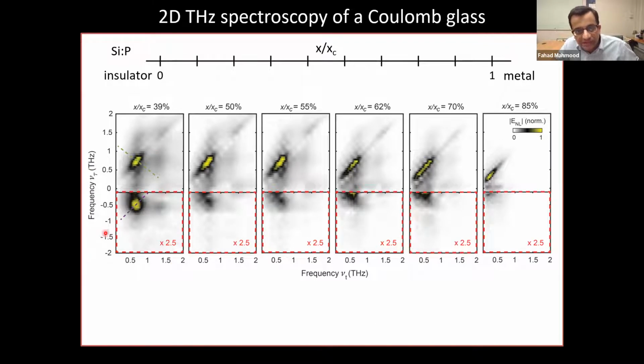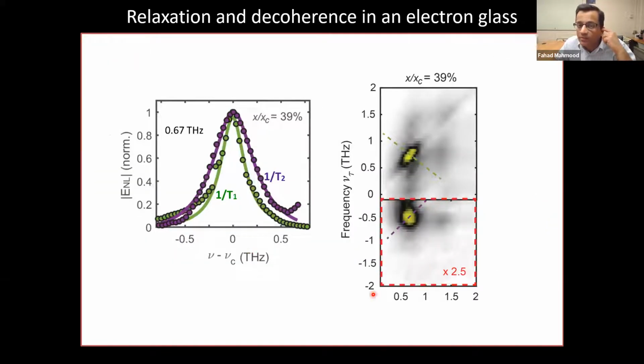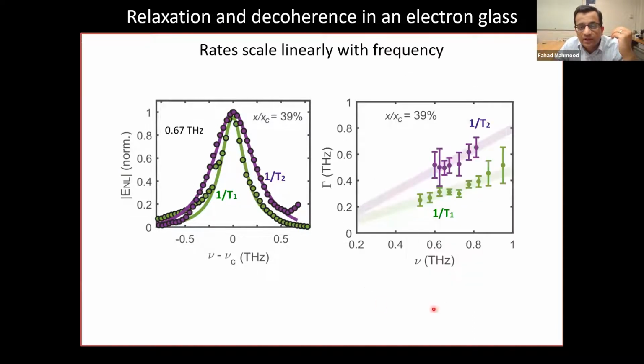We can take these line cuts that I was describing, and from there extract these 1/T2 and 1/T1 times. So that's what I'm doing here, just to show you this is a simple Lorentzian fit. And then you can do this as a function of frequency. And this is what we get. This is extracting those scattering rates as a function of frequency. And what's very interesting to note is that these scattering rates are essentially linear in frequency. They don't behave as what you would expect from a Fermi liquid, where they should go as omega squared. They're going as omega.